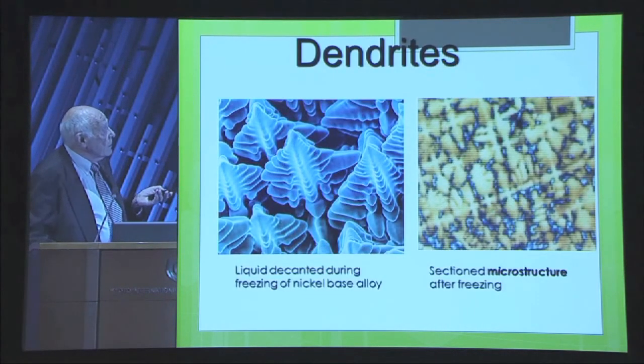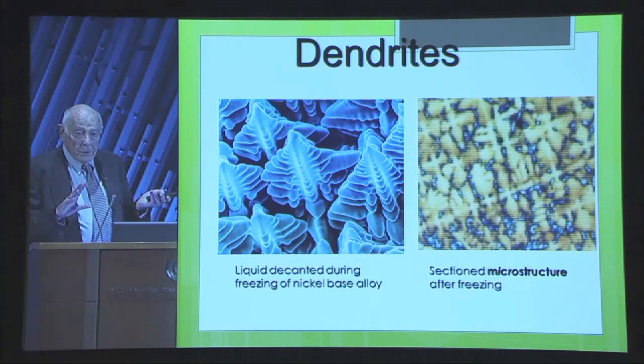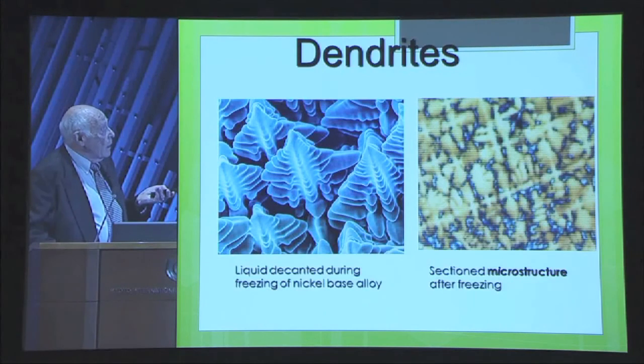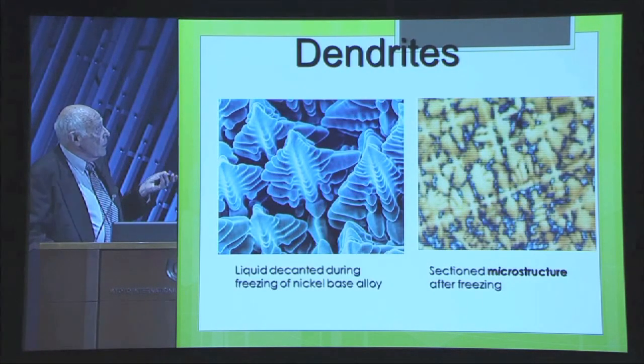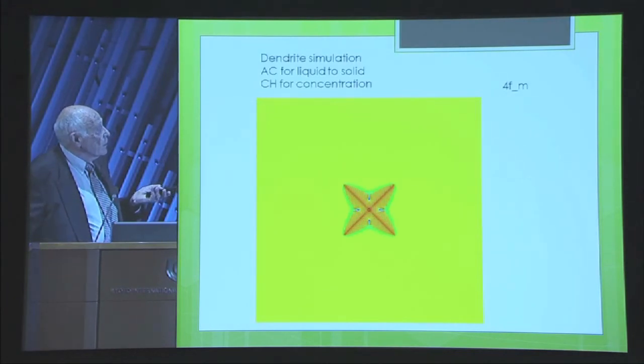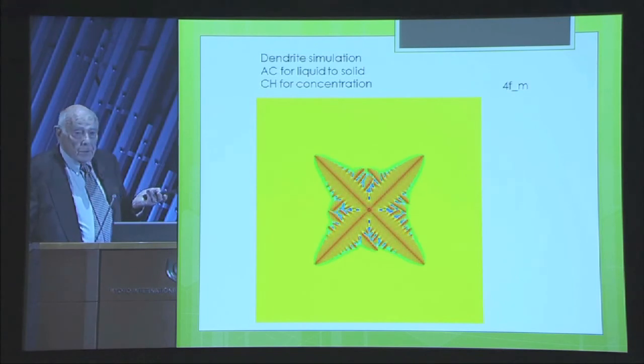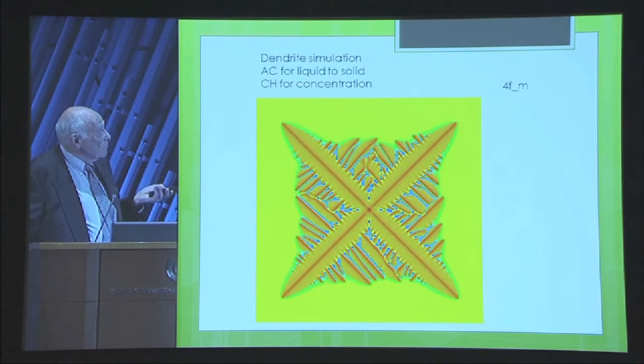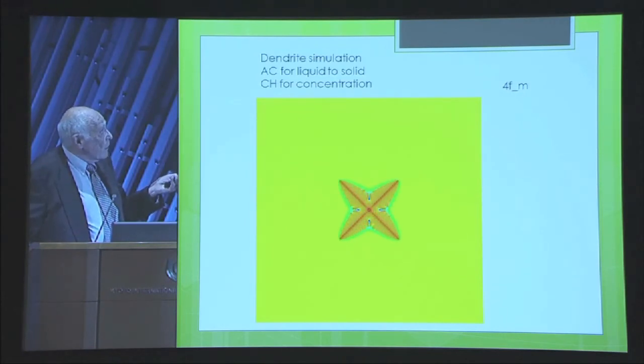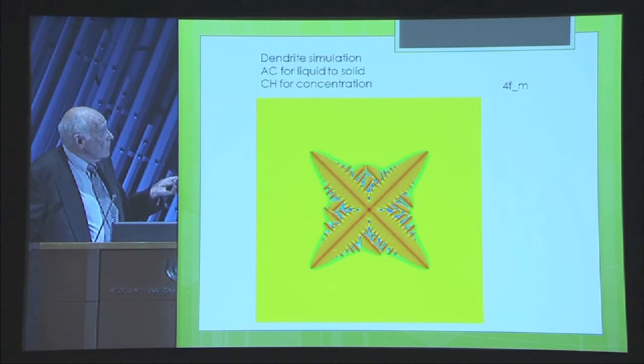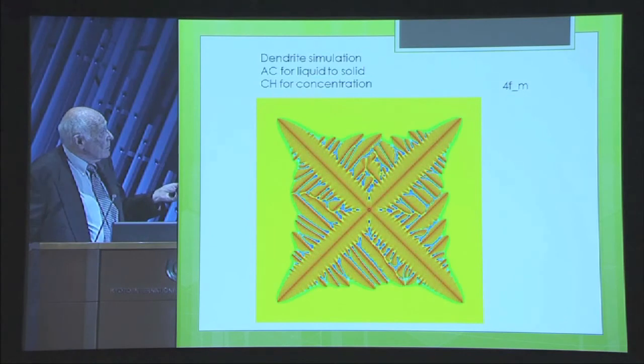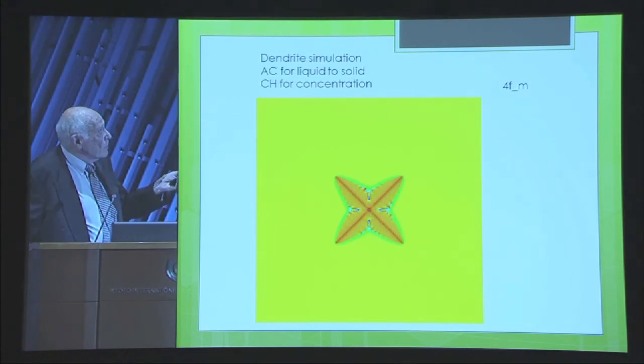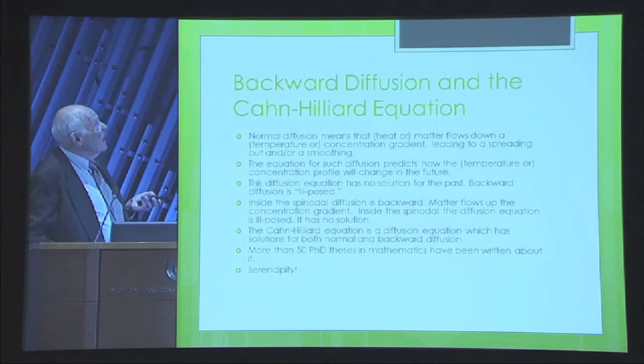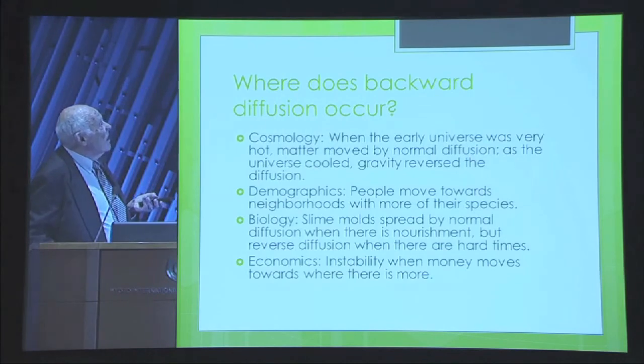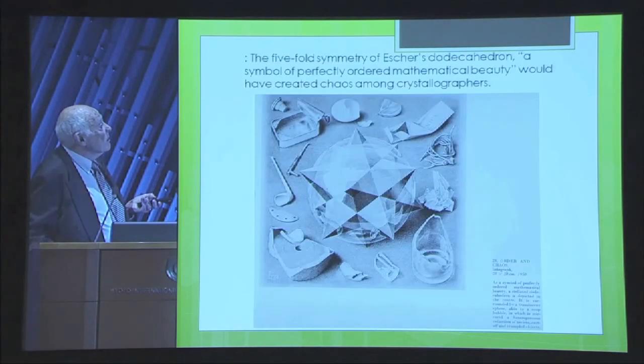Here are dendrites, and the only important thing about this is that the combination of the two equations for these two different processes are used to solve the dendrite problem. And here is an example of a computer calculation for a dendrite. You see here the darker brown is where the alloy element concentrates here and in the center, and the green is the temperature in the liquid around the growing dendrite. So let me, all right, where does backward diffusion occur?